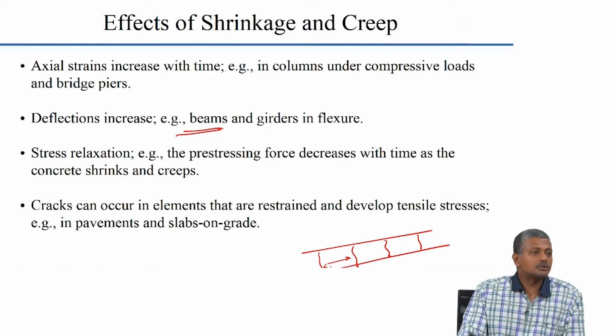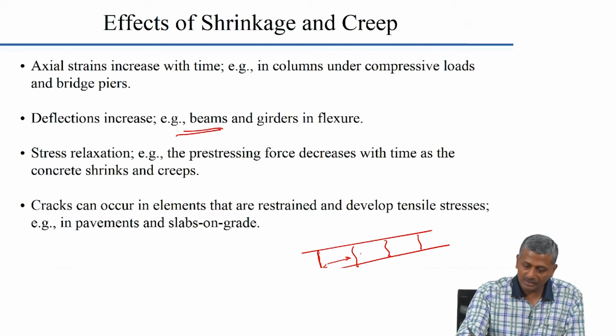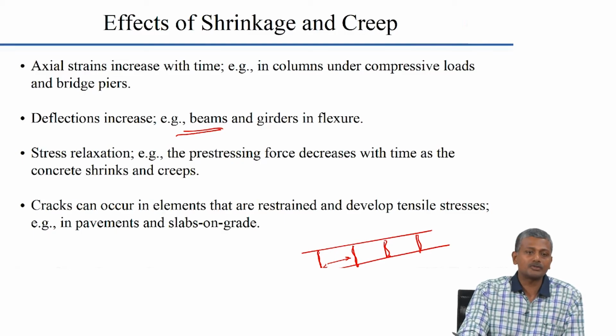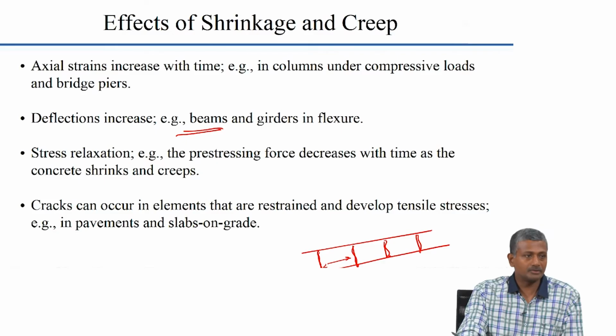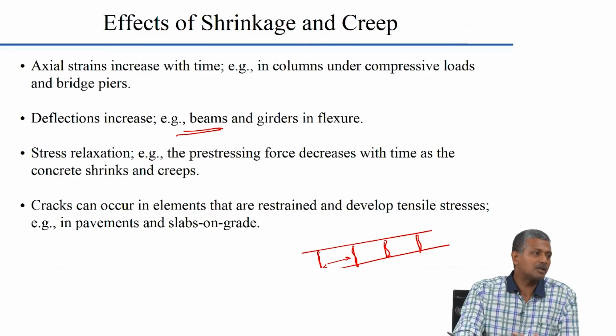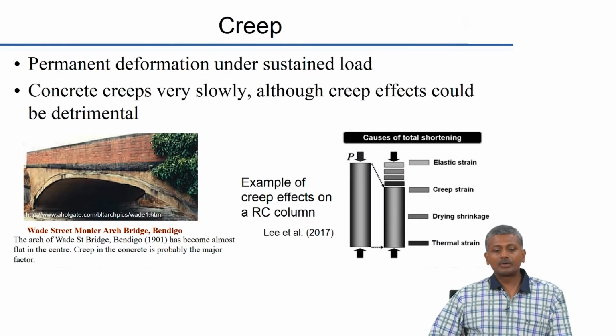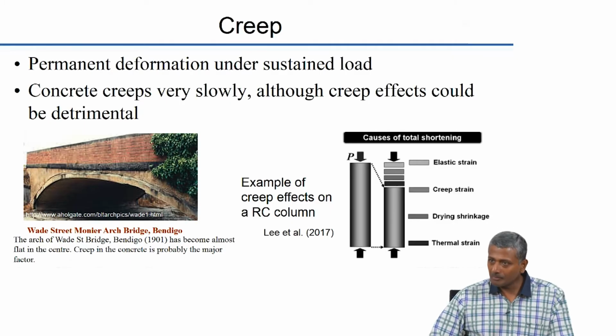Okay. So, what do we generally do in the case of pavements? We give joints exactly at these locations which are likely to crack. We actually make joints and then we seal those joints to ensure that moisture does not get into the pavement, right. So, joints are created primarily because of the effect of shrinkage. Now, creep is obviously related to the permanent deformation under sustained load. Concrete creeps extremely slowly, but then creep effects can be detrimental to the performance of the concrete.